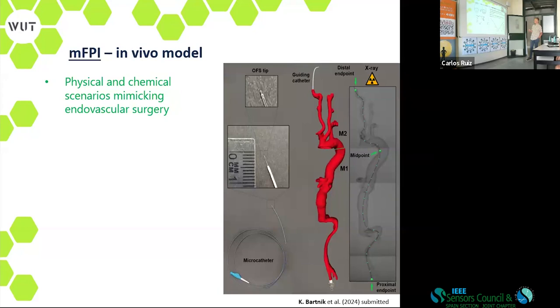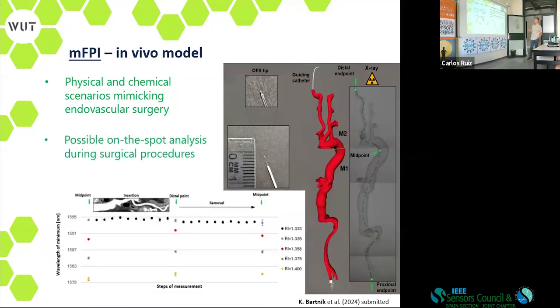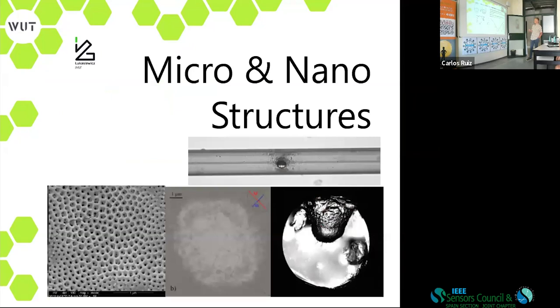So we are monitoring the optical signal at the different stages of this procedure. X-ray was applied at the same time, and you can see that when we measure the refractive index at the entrance, so when the probe was out of that, it worked well. Then we pushed at different stages. We pushed the probe and it is still operating. Then outside it was still working. Then we pushed it back and it's still working. So it means that all these curvatures inside the human body in the real case scenario do not affect that much the performance of the system.